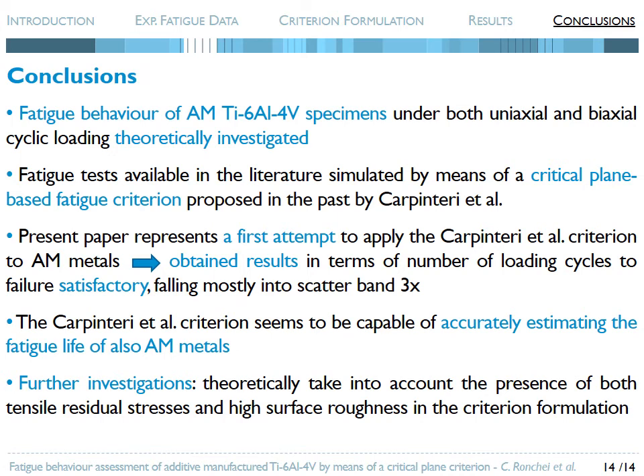And now let us move to the conclusions. In the present research work, the fatigue behavior of AM Ti-6Al-4V specimens under both uniaxial and biaxial cyclic loading has been theoretically investigated. In particular, fatigue tests available in the literature have been simulated by means of a critical plane-based fatigue criterion proposed in the past by Carpinteri and co-workers.